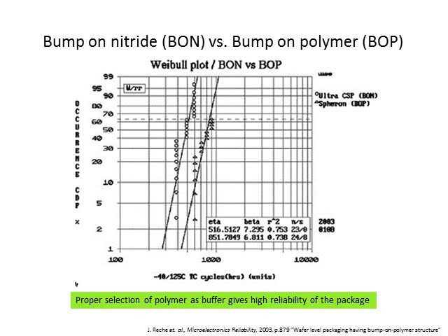Indeed, when we plot the failure rate against thermal cycling steps, we can clearly see the improvement of the bump-on polymer structure compared to the bump-on nitride structure. The message here is that by selecting the proper material as a buffer layer, we can get a higher reliability of the package.